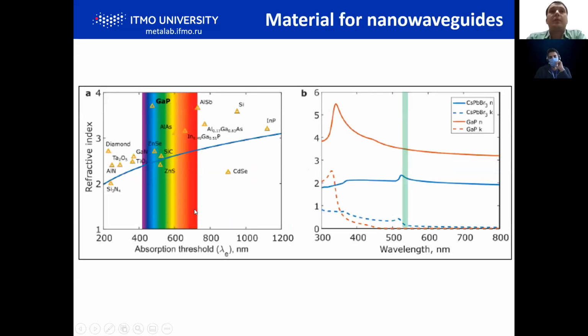Once we have good lasers for the green range, we have to forget about silicon photonics, because silicon has high losses in the visible range, and we should start to find a good material for the visible range. One of the best materials for creating nanophotonic waveguiding systems is of course gallium phosphide, because it has a very high refractive index, almost up to 4, even higher sometimes, and it's lossless in most of the visible and infrared range. Here you see the dispersions, the refractive index and imaginary part, for gallium phosphide and for perovskites. And you see that the emission is in the lossless range of gallium phosphide.